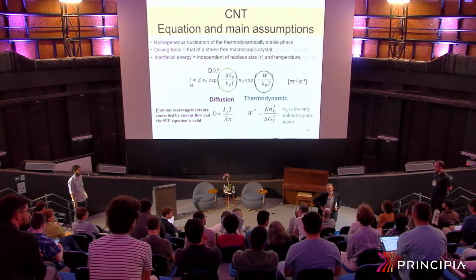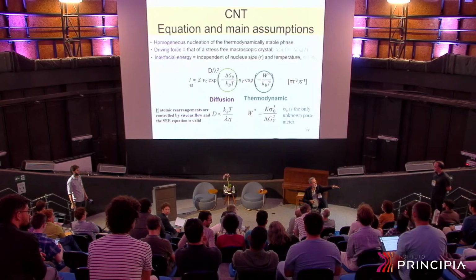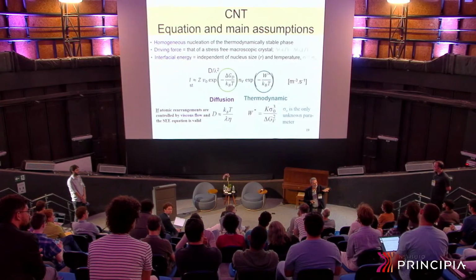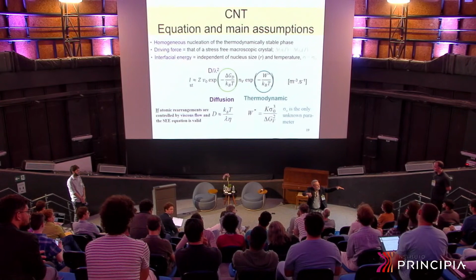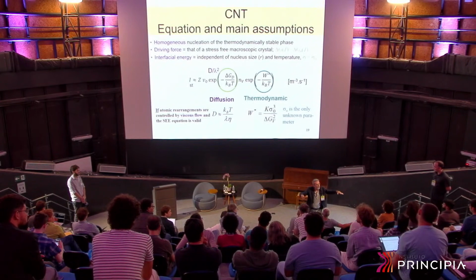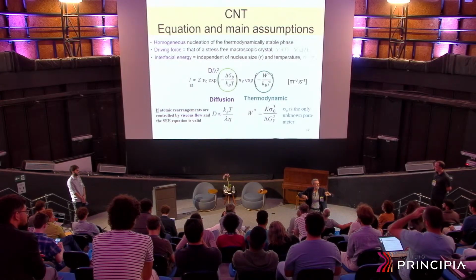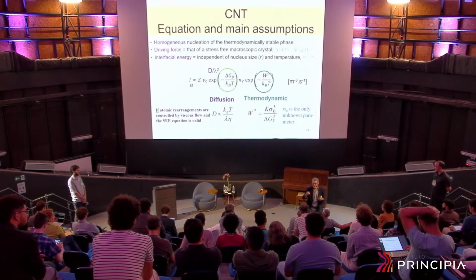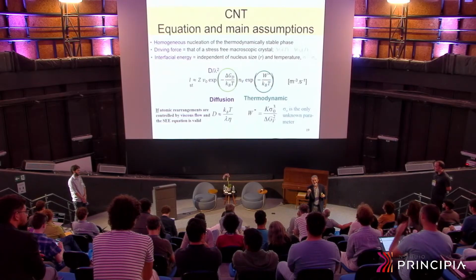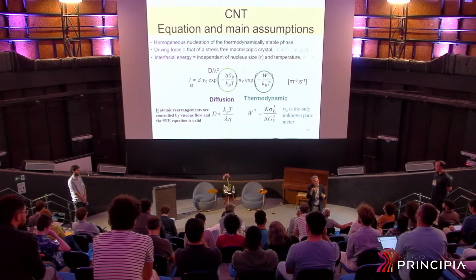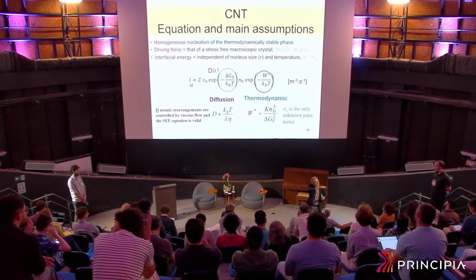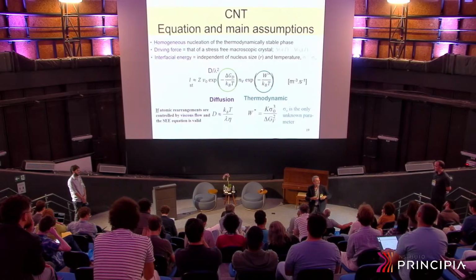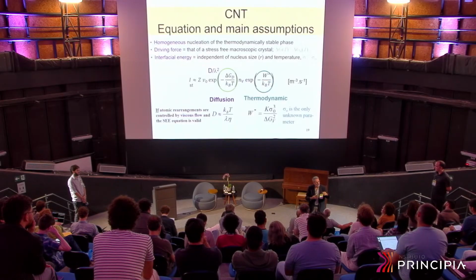If you use the value for the flat, macroscopic crystal, you have huge discrepancies. We did this for Lennard-Jones, which is a very simple potential. We calculated the variation of interfacial energy with temperature, extrapolated to the melting point, and it more or less agrees with the value for the flat interface theory. I can send you this paper.